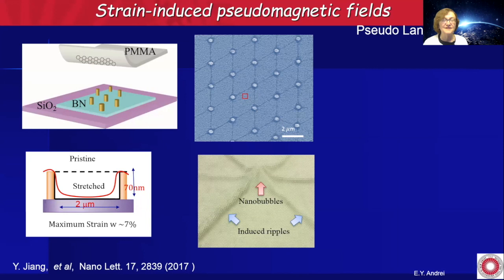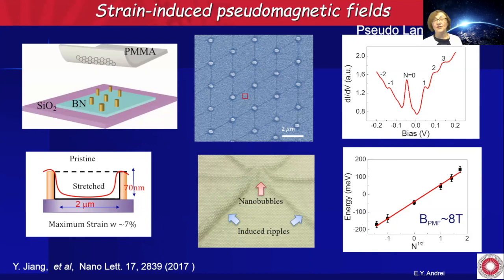So now we go into one of these regions here and we measure the density of states, the spectroscopy. And lo and behold, we see beautiful Landau levels appearing. Again, just as before, we can fit the sequence of energy to the square root of the Landau level index, and we get a magnetic field which is kind of low, but this is a function of the geometry of this pattern. But we can induce a pseudomagnetic field of about 8 Tesla. So this gives us a pathway to continue to get much higher pseudomagnetic field and to eventually get flat bands and possibly correlation-induced phases, correlated phases.